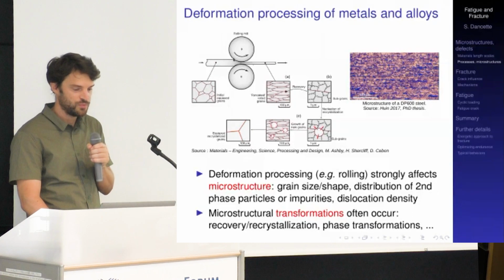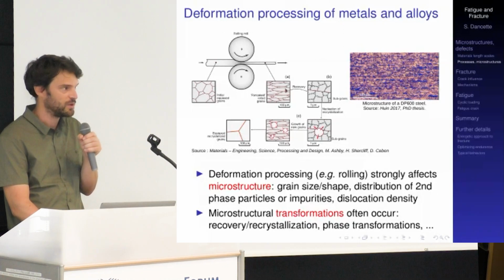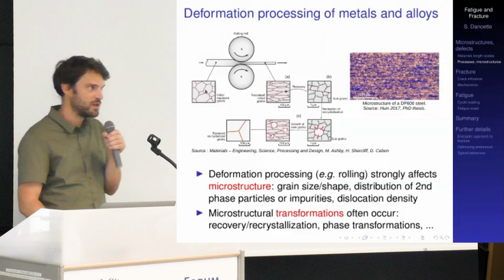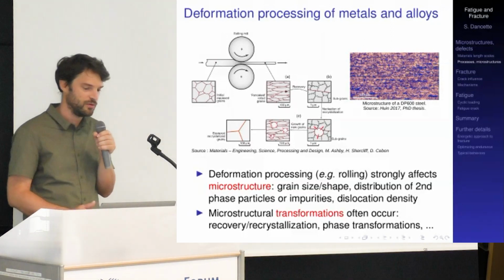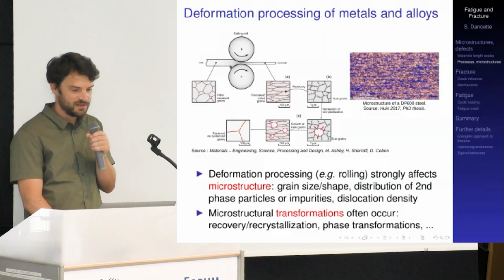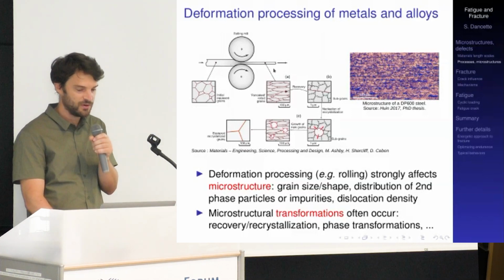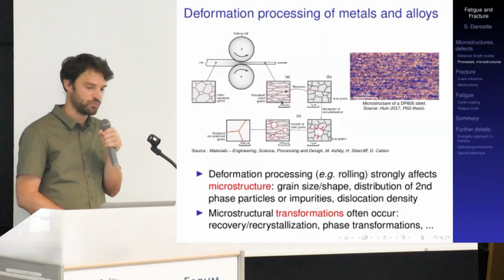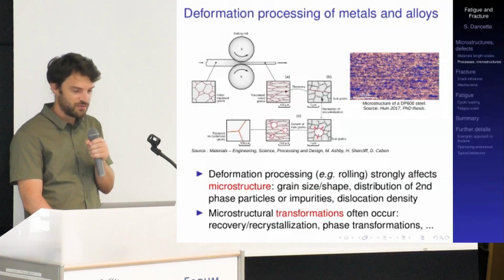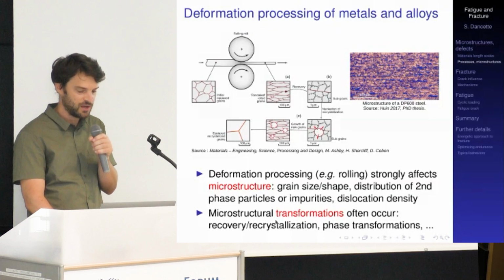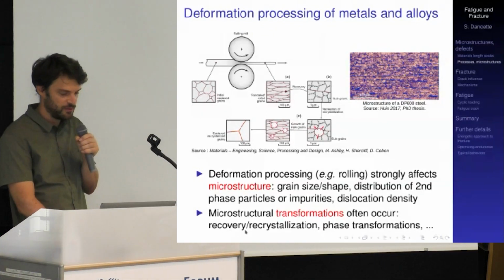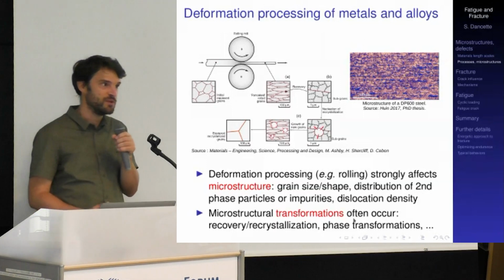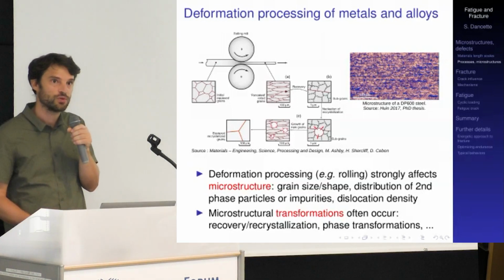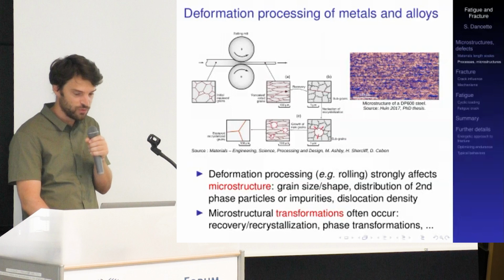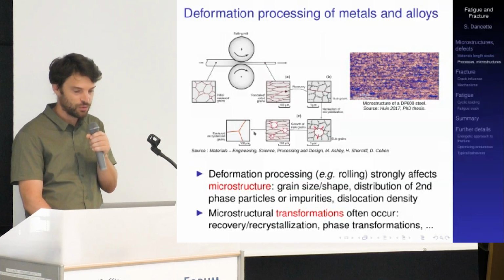And again, if you subject a metal to that kind of rolling process, then you see that there will be some strong evolution of the microstructure inside of the material from the initially equiaxed grain, potentially, that we can find in the core of a cast slab, for example. And these grains here will be severely deformed and severely reoriented, let's say, in the course of the process, implying potentially several phase transformation or microstructural transformation mechanisms like recovery, recrystallization of the material, but also in steels, for example, there will be definitely some phase transformation, some change of crystal structure from high temperature to low temperature. And all of this, again, will have a strong impact on the resulting microstructure.